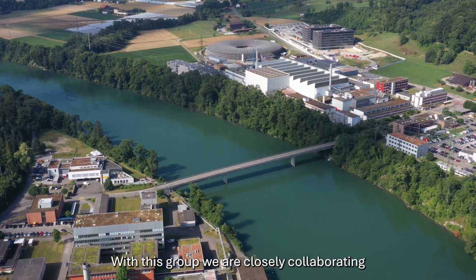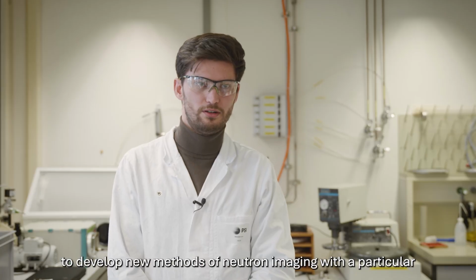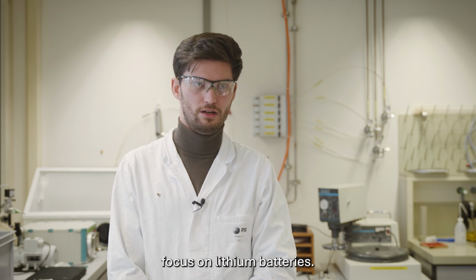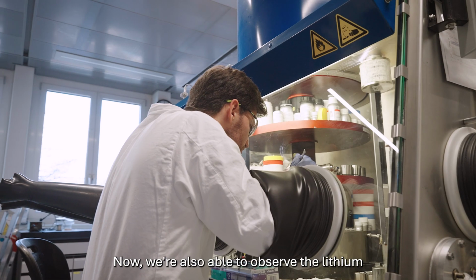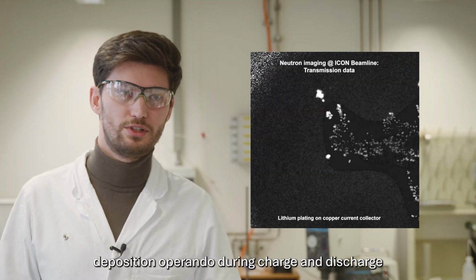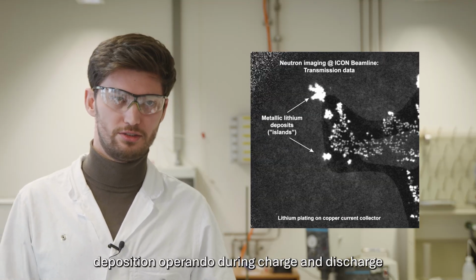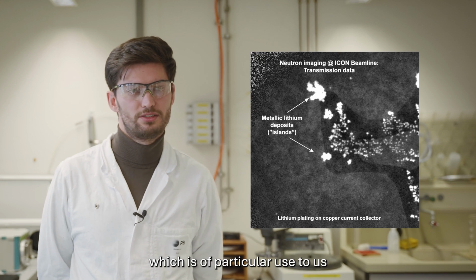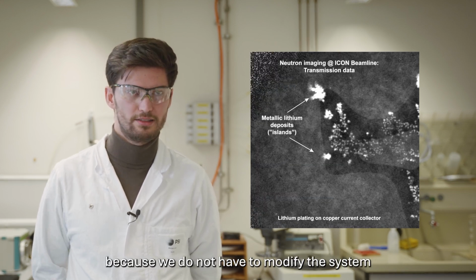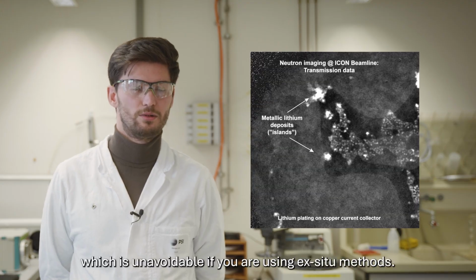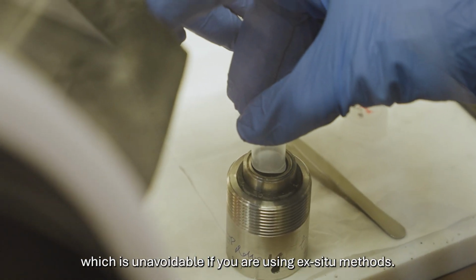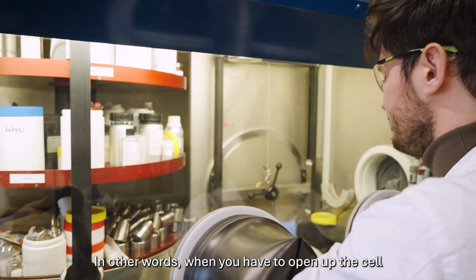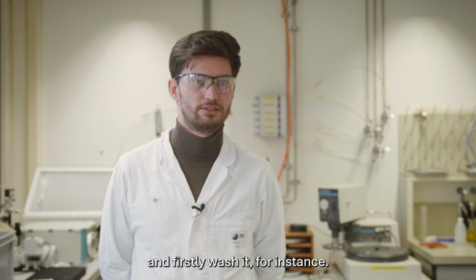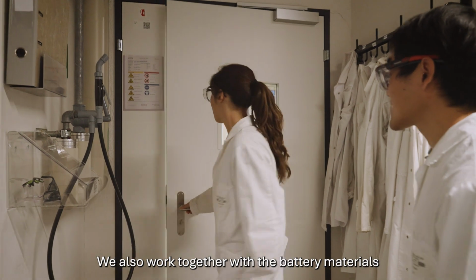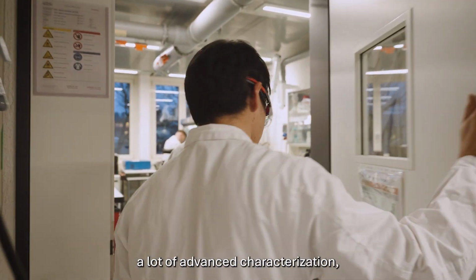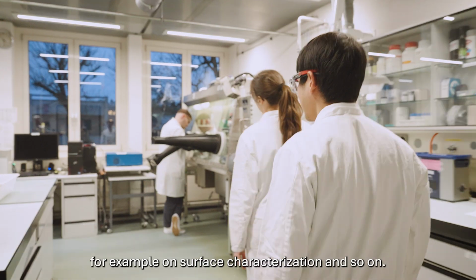With this group, we are closely collaborating to develop new methods of neutron imaging with a particular focus on lithium batteries. Now, we're also able to observe the lithium deposition operando during charge and discharge, which is of particular use to us because we do not have to modify the system that we're interested in, which is unavoidable if you're using ex situ methods. In other words, when you have to open up the cell and firstly wash it, for instance. We also work together with the Battery Materials and Diagnostics group on a lot of advanced characterization, for example, on surface characterization and so on.